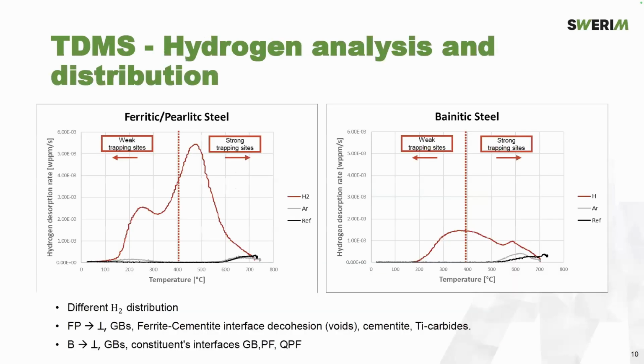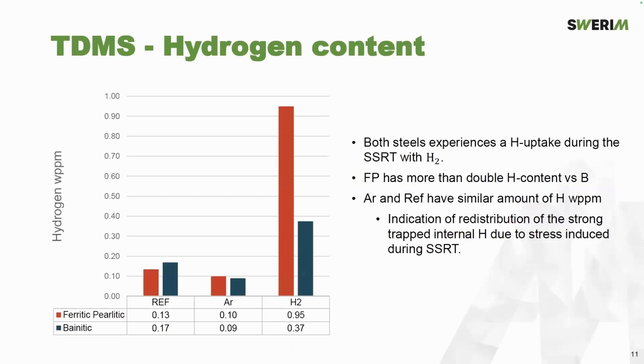From this SSRT test, we performed the TDS after removing the shoulders of the specimens, and we can see a different hydrogen distribution in both materials, with different trapping sites and different amounts of hydrogen in both. Here we can see 3 different curves: one hydrogen test, one argon, and one reference. The most important thing here, within the argon and reference, is that we could see some kind of redistribution of hydrogen after this strain rate test, in both kinds of curves. This is in a numerical way. And of course, the ferritic-pearlitic has a higher uptake of hydrogen.